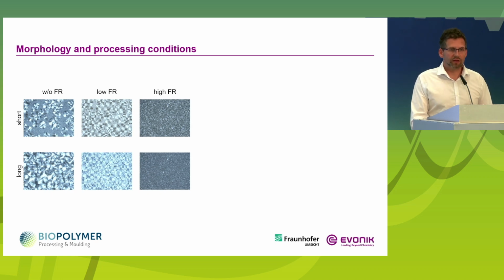And when we now add a low content of flame retardant, we see that we have, even at short cycle times, a crystallization, but when we now incorporate more flame retardant, we disturb this crystallization. And so we see already at this point that it's difficult to reach all the properties we need for the industrial use of the PLA.